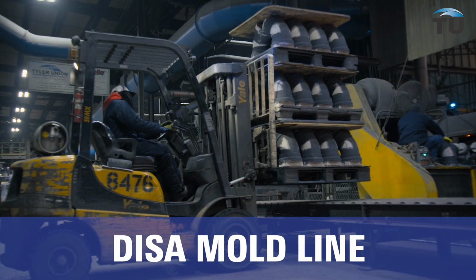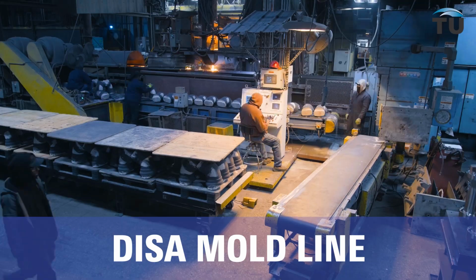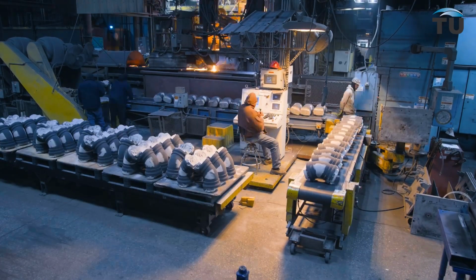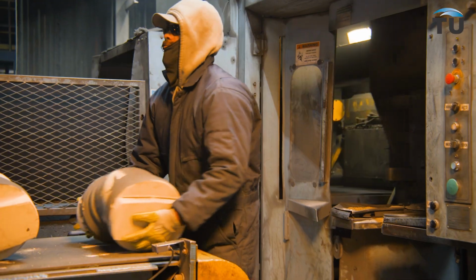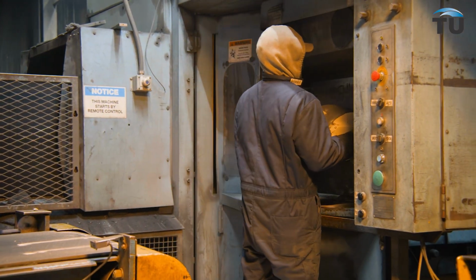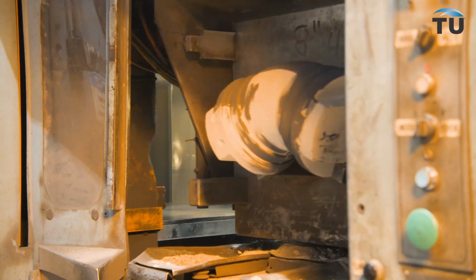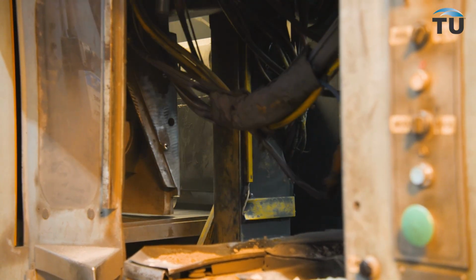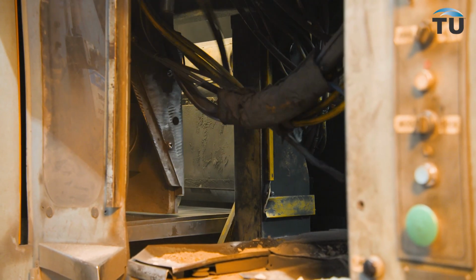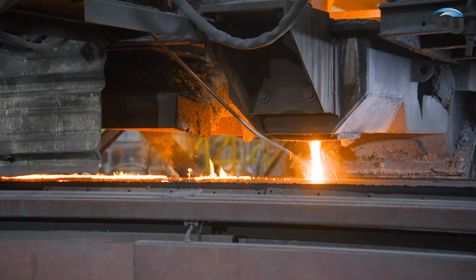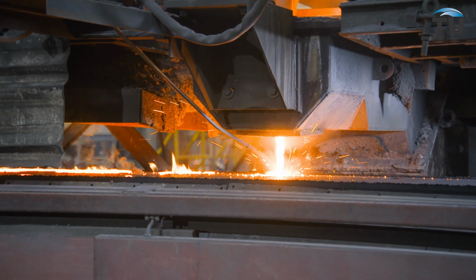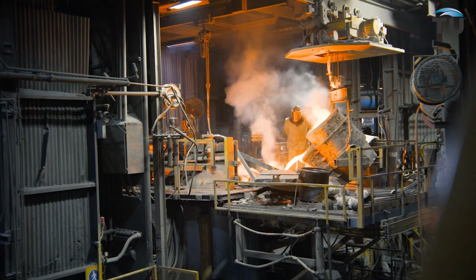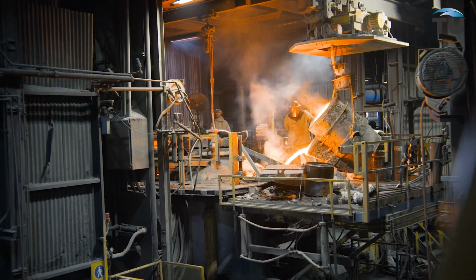Our DISA molding line produces the highest volume of products, running over 300 cycles per hour. The DISA produces most of our 10-inch diameter and smaller castings. The mold is vertical, and a core mast uses vacuum pressure to hold the cores in place until inside the mold. Molds are filled with iron from a pressurized furnace using a stopper rod, and the furnace is continuously filled with iron from the cupola.